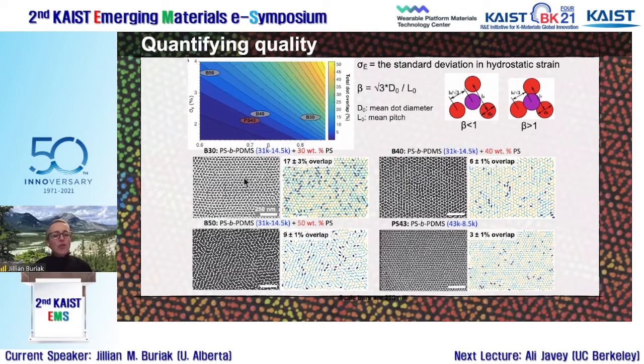But Brian would write an algorithm, and then we would feed these SEM images into the algorithm, and you could see the one here with 17 plus or minus 3% overlap. The dots that are colored in blue are in fact in contact with each other. And so if you're interested in bit patterned media, that's telling you that actually 17% of these dots are in contact with each other. But once you have this algorithm, you can then actually quantify quality.